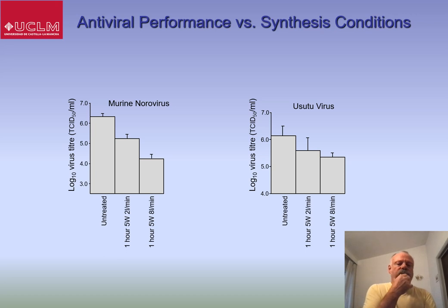Again, because of the noise, we can't be quite so specific in the case of the Usutu virus, but again, it seems to show the same trend, that you get a better performance with the polycrystals. And we think the reason for this is that the nanoparticles have more facets, more edge atoms, and so on in the case of the polycrystals, and it seems that these bind more strongly to the proteins.